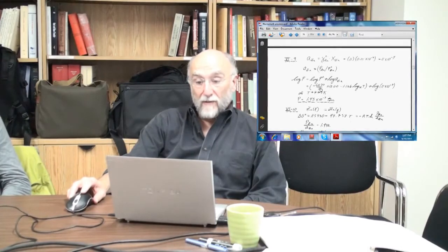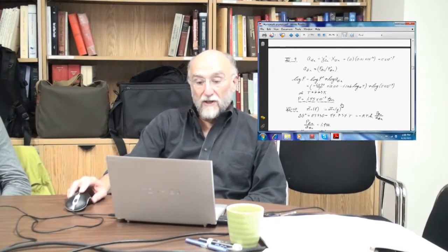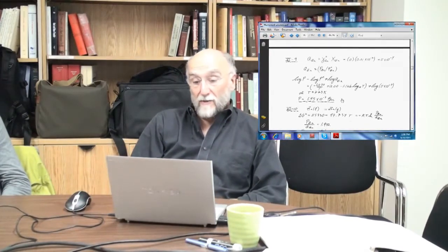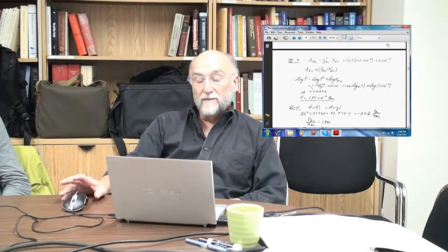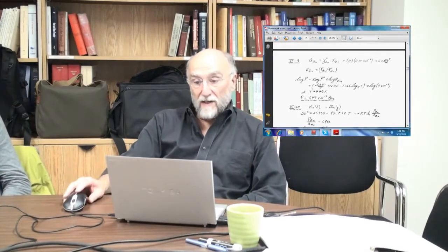You've got to reach 1.45 times 10 to the minus 3 torr, the minimum pressure that you have to pull on a vacuum in order to get the partial pressure down to that. If you have a higher pressure, then you'll have a higher activity, and hence a higher mole fraction.